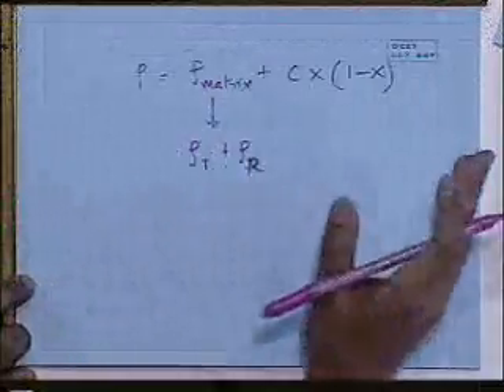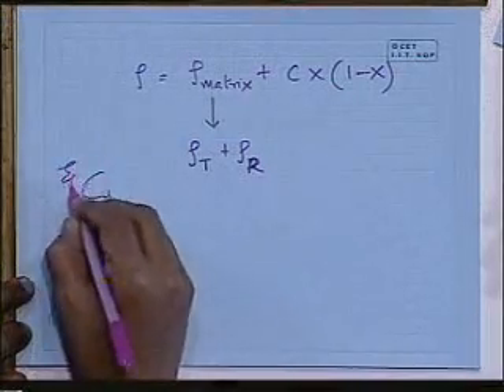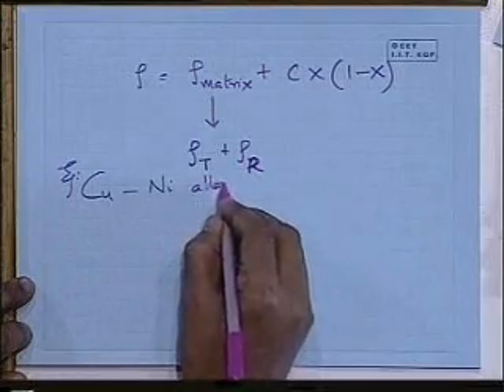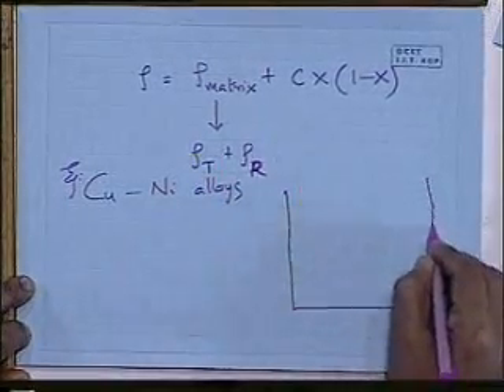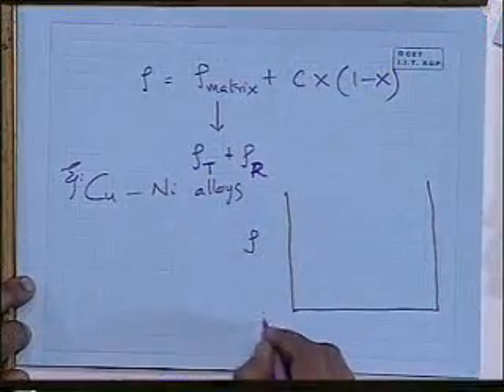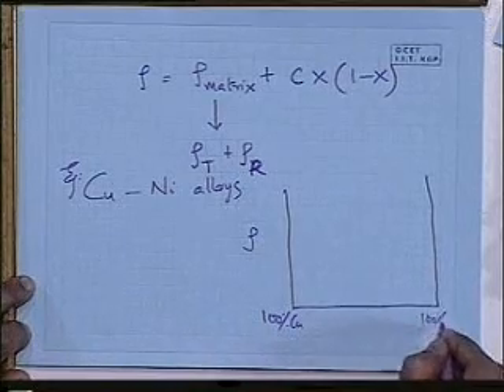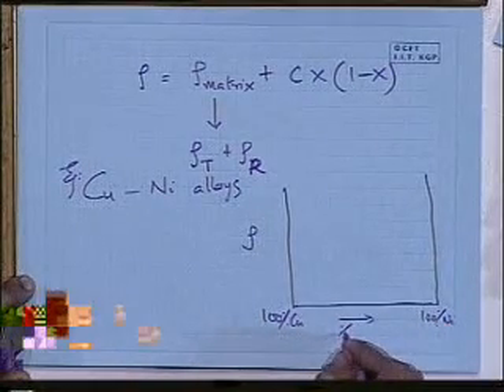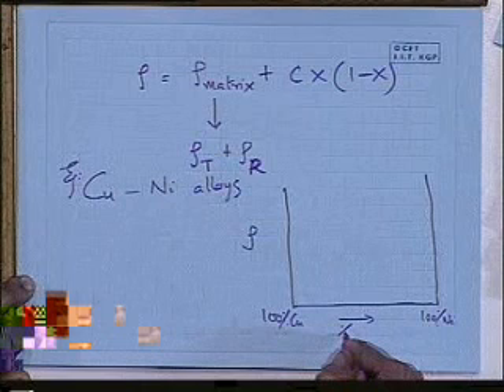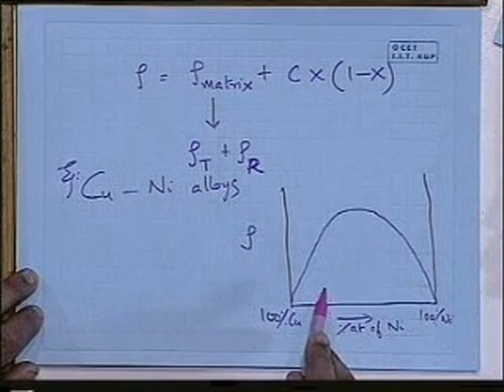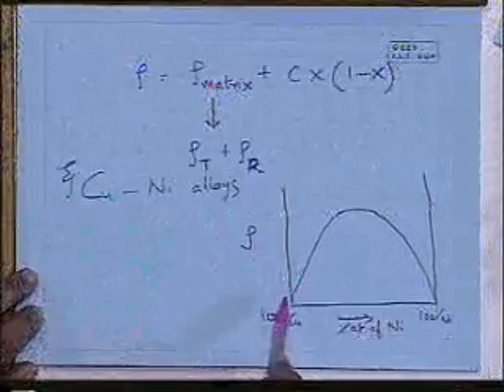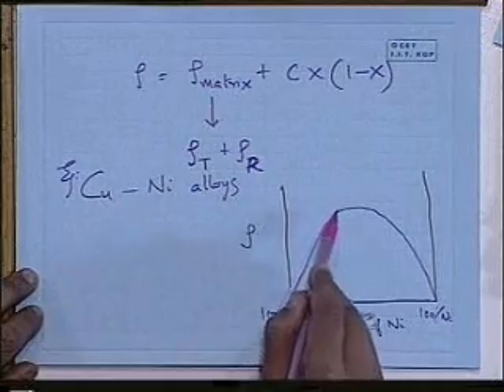You can see an example, say for copper nickel alloys. If we plot the resistivity versus concentration, one end here we have 100% copper, the other end we have 100% nickel, and it's increasing atomic fraction of nickel, somewhat like a phase diagram, but we are plotting it as the resistivity. It looks something like this. The resistivity goes on increasing as we put in more and more nickel, and then there's a maximum, and then the resistivity decreases. How do we explain this? Here it is pure copper, right? And as we introduce impurities, it is getting more and more resistive because of this coefficient. But this end of it is pure nickel.